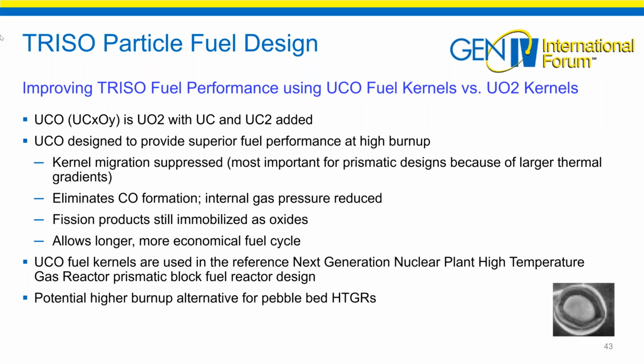Do we have fuel that is better, UCO versus UO2? In UO2 fuel, and this is why I pulled up this slide, kernel migration occurs: the kernel moves because of the thermal gradient, and the buffer tears off, and you'll actually see it move within the particle. When that happens, the kernel gets put right up against the silicon carbide and pyrocarbon layer, and you'll see palladium attack, which is not good.